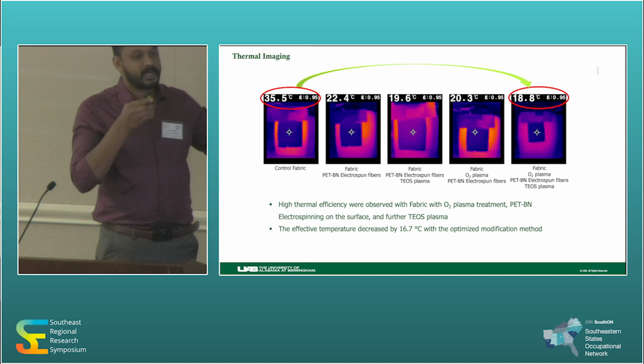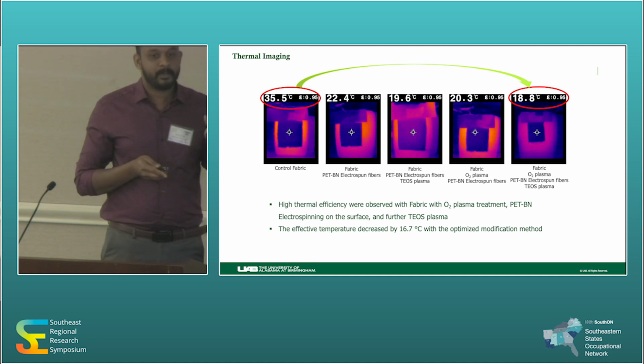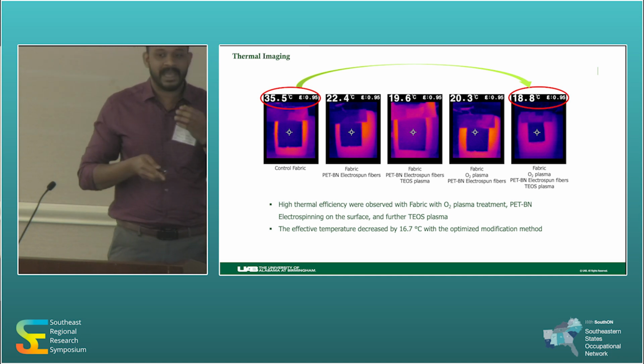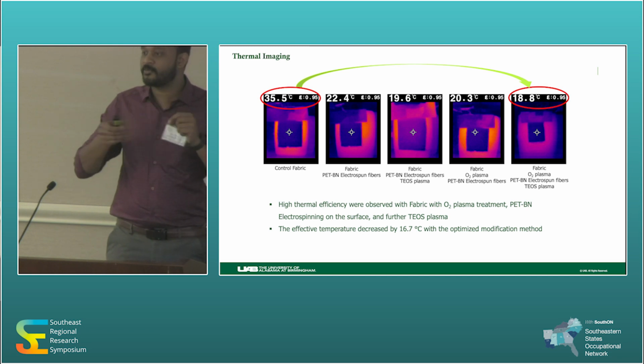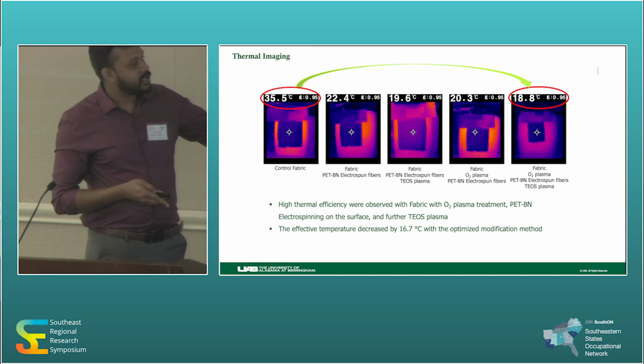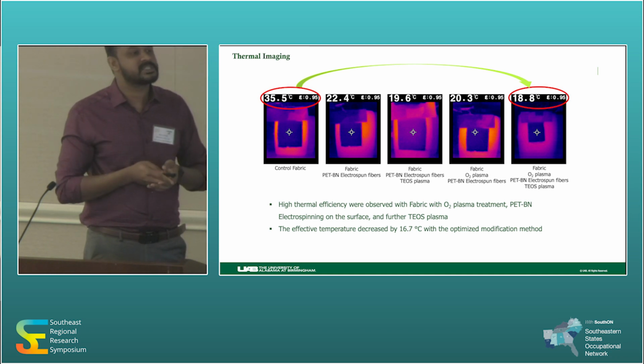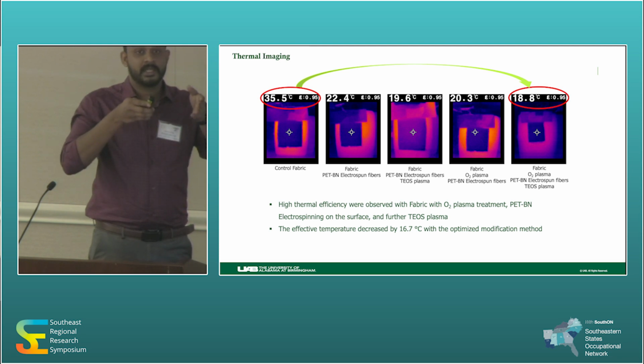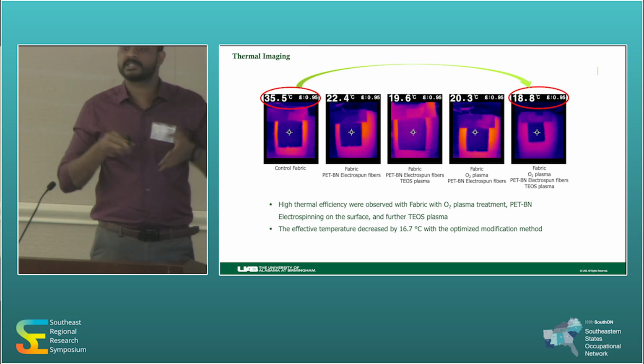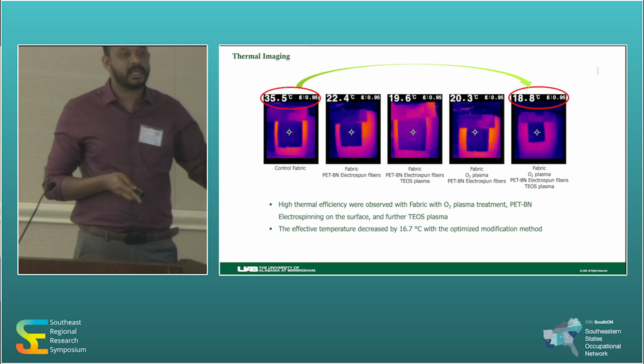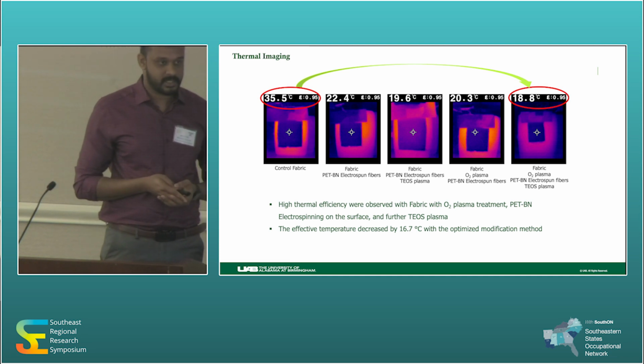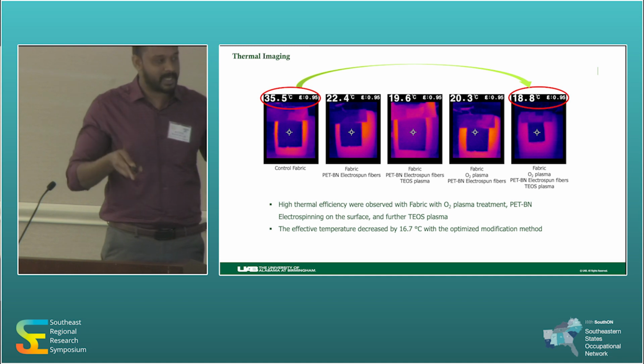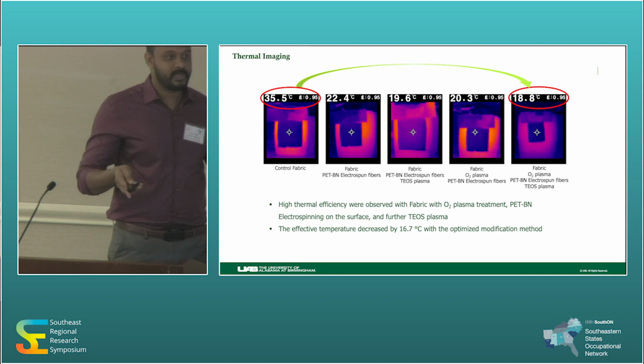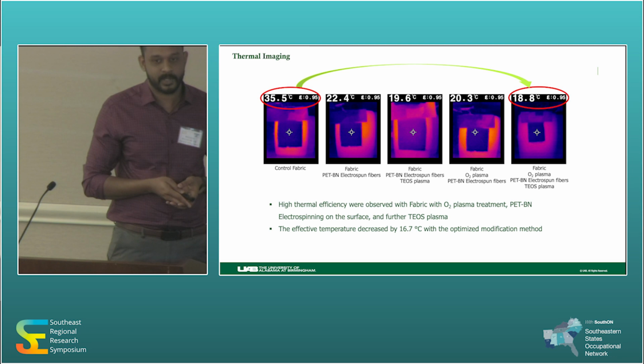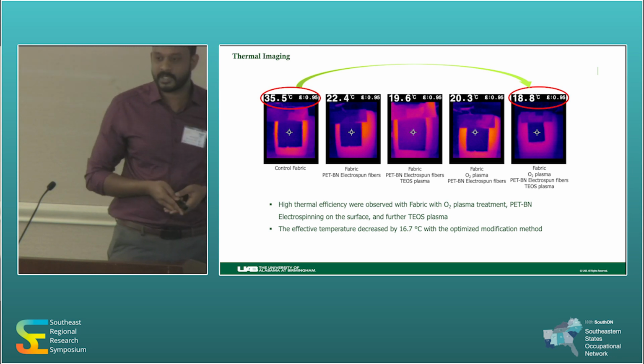And there is one already reported paper. They made use of the boron nitride nanoparticle with some extrusion principle to make the fiber threads for making the fabric. At that stage, they reduced the temperature by 16.1. We have a reduction of 16.7 degrees. So by making use of both these nanoparticles, we find a much lower effective temperature with our novel fabric surface.